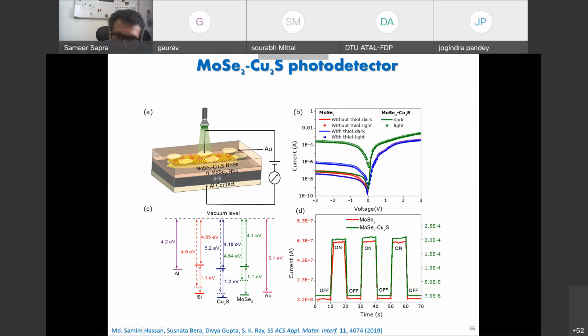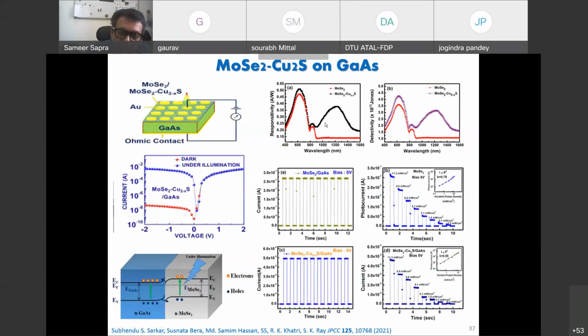Not only that, this is not just visible light, but if you actually take a spectrum of the entire process, you see this is also active in the IR region, and this is very useful for space applications and defense applications. Yes, so with these IR active materials, and why they are IR active is because it's not Cu2S, but it's actually Cu2-xS, and that exactly comes to 1.97. So Cu1.97S, as we've seen. And because of that, there are a lot of holes that get doped in the system, and these are active in the infrared region. Okay, and you get this infrared. You see, you don't have any infrared response with MoSe2.